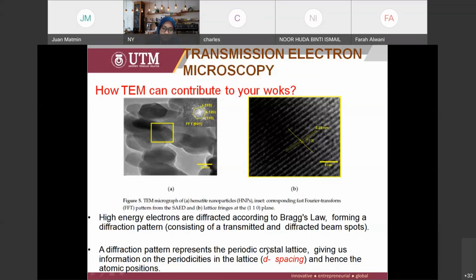And based on that, we are going to look at the crystal lattice and based on the d-spacing as well. So the d-spacing here contributes to 0.25 nanometer, which is common, is small for hematite. Okay, this is very true for the hematite. And when we look at the photographic image here, you know that these particles are corresponding to the hexagonal structures.